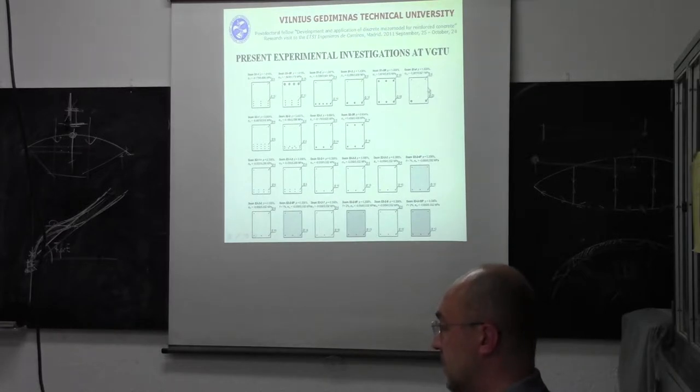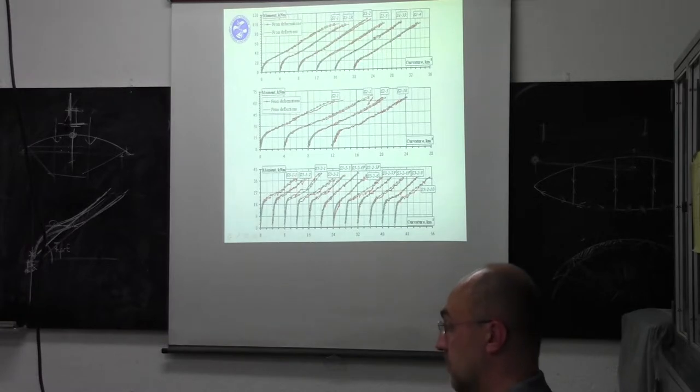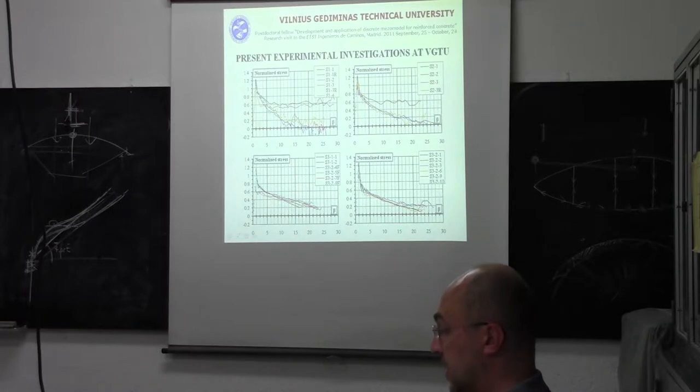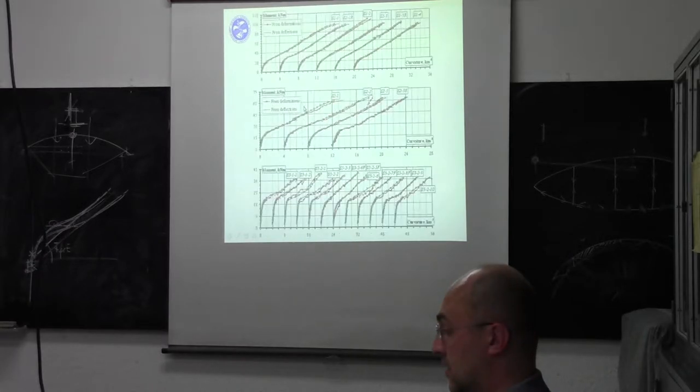Top elements had 1% tensile reinforcement ratio. Second line had 0.6 reinforcement ratio. And bottom two lines had 0.3 reinforcement ratio. Then we measured moment curvature diagrams and obtained tension-stiffening relationship. As you can see, the previous results were...